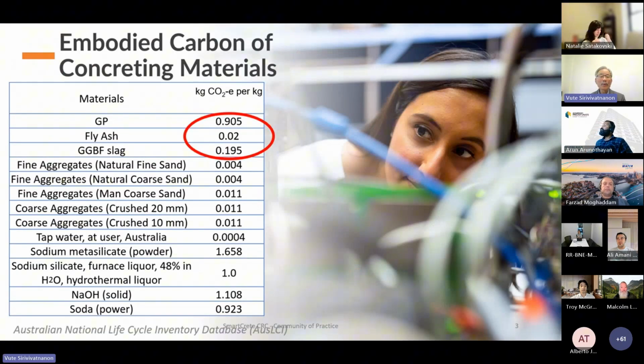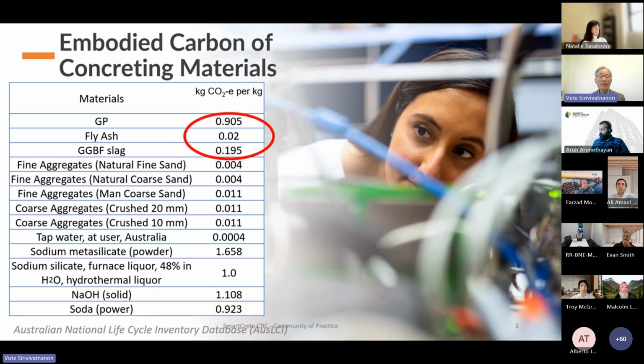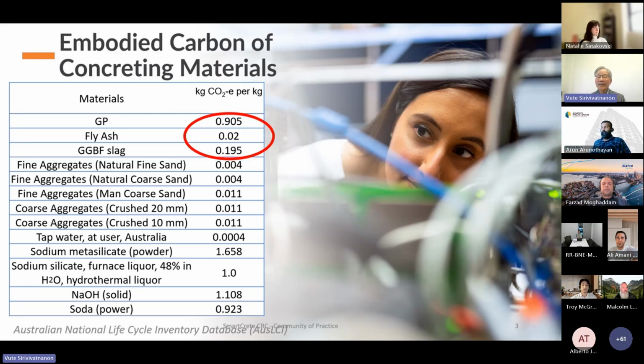And I would only cover, I guess, the use of supplementary cementitious material in the production of low carbon concrete. The reason for that is quite clear. If you see the embodied carbon of the raw material, either the GP cement, fly ash, or slag, you can see that if we can introduce blended cement, cement with fly ash or slag, or with both for that matter, you can actually reduce the embodied carbon quite substantially just by the fact that fly ash and slag have much lower embodied carbon per mass compared to general purpose cement.